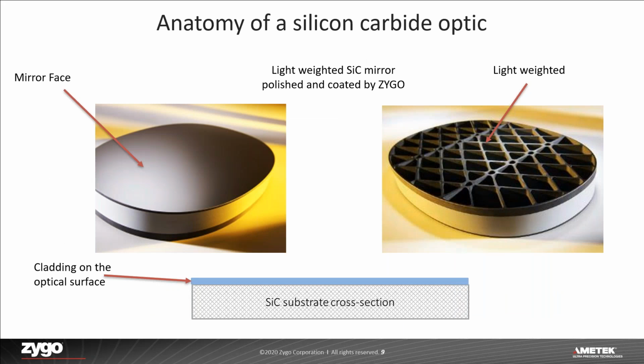As we get into the anatomy of a silicon carbide optic, the mirror face of the silicon carbide optic is made up of the face sheet with a cladding material deposited on top prior to polishing. Bare silicon carbide usually doesn't meet the surface quality or roughness requirement needed for a laser quality surface. You need a cladding to finish the surface to get to that laser quality. However, there are some exceptions.